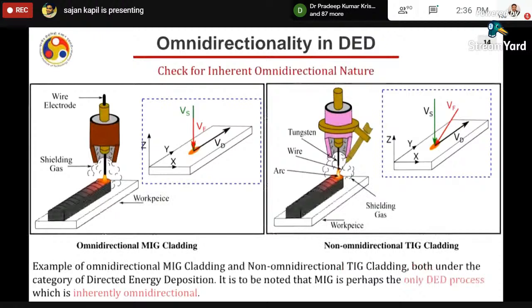Like I explained, you see in this diagram on the left side, this is the MIG welding. Here, VS and VF both are collinear. Both are coming from the top, because my VF is the source of VS. And hence, they will always remain perpendicular to VD wherever you move on the substrate. In that case, it is omnidirectional. But if you see TIG, VS is vertical, created by the tungsten, while VF is fed from the side. Now, assume that VD is in the X direction. In that case, the angle between these two may change, and hence issues will arise. And this will keep on happening. The relative position may keep on changing, and hence the angle keeps on changing, which will create the issue for the omnidirectionality.